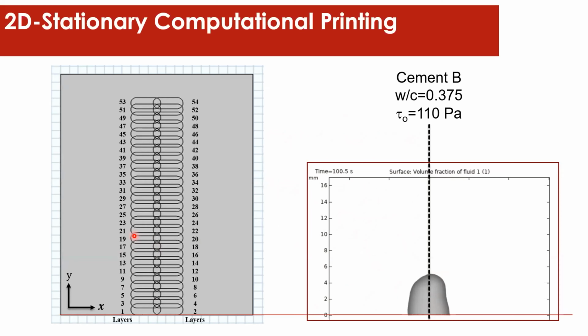So these are the stack of layers that are going to be printing a double wall, because we are printing a double wall hollow cylinder. So the printer is coming past the outer layer and the inner layer, and the material is wicking and slumping into it. I selected a particular object here that will fail at some point because I wanted you to see that this 2D technique, although it is two-dimensional and computationally very efficient, can actually capture the dynamics of a failure. And in a bit, you will see that there is a collapse of the wall.